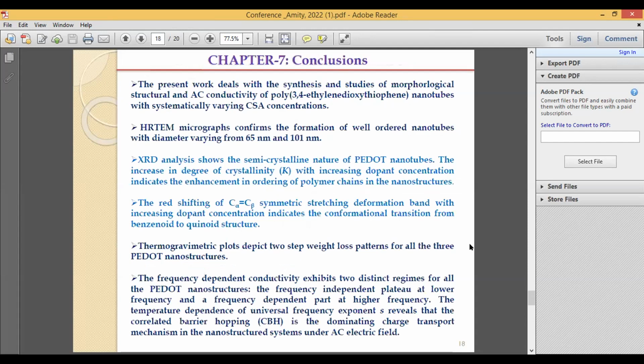And then conclusion. From the micrograph, we can say that we have successfully synthesized well-ordered nanotubes by using CSA as a dopant, which acts as a soft template in our case. The average diameter of the nanotubes is found to be 65 nanometers to 101 nanometers. From the XRD pattern, we have also seen the diffraction pattern, and the enhancement of crystallinity in our case for the highest sample.